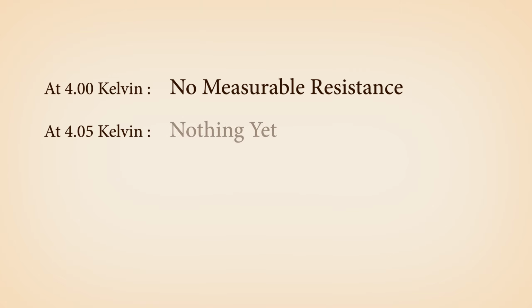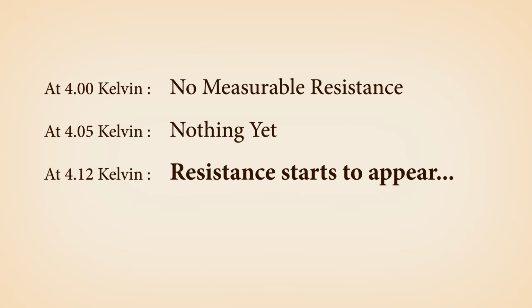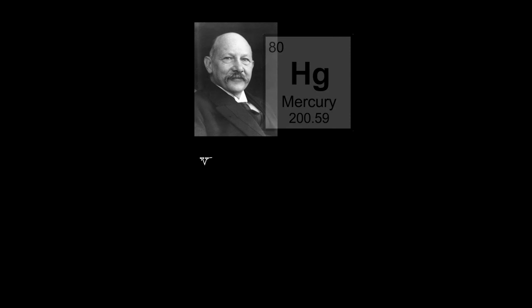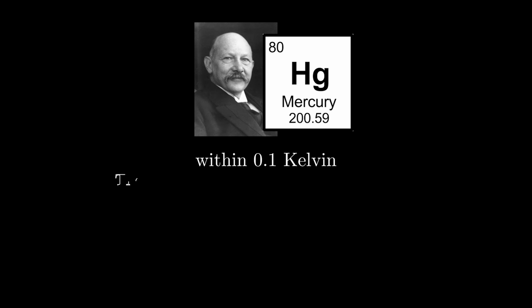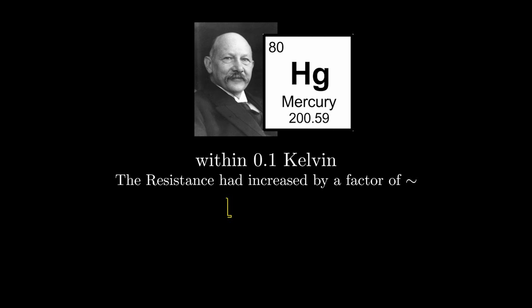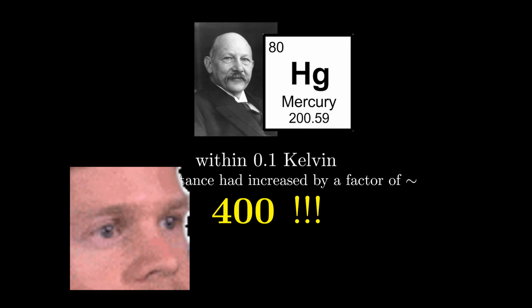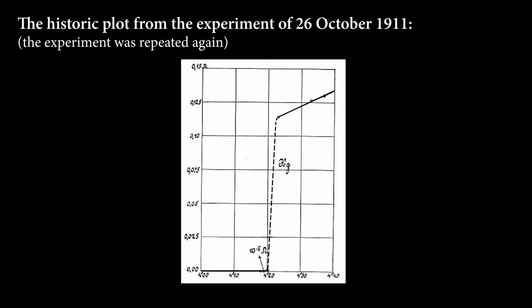At 4.00 Kelvin, no measurable resistance and no indication of resistance rising either. At 4.05 Kelvin, nothing yet. At 4.12 Kelvin, resistance starts to appear. Onnes reported that within 0.1 Kelvin, the resistance of the mercury sample had increased by a factor of almost 400. This is crazy stuff, and there was no doubt about it. The resistance was literally too small to be measured, and really practically zero. And this drop was very abrupt, occurring at 4.2 Kelvin.